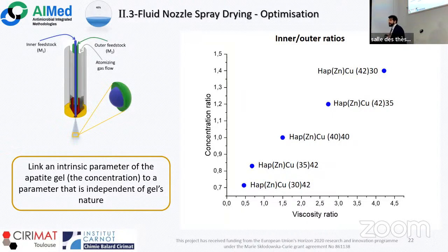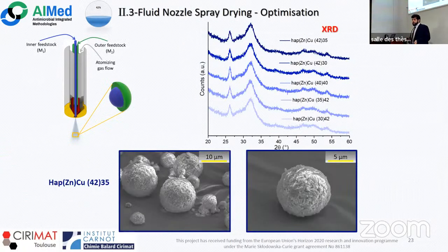that can change with the ion, the counter ion, almost everything, to the viscosity, which is an independent parameter that can be optimized, can be easily measured, and can of course be extended to systems that are not apatite gels. So at first we synthesized these particles, and you can see a good coherence of the diffractograms with the usual structure that we have seen along this discussion. And also the morphology and the rugosity are the same that we have already seen.